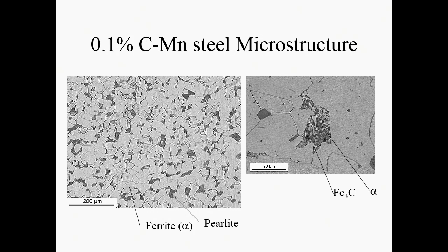With pearlite, the iron carbide is present in very thin layers and it's laminated structure, and this is a very tough structure, and this is very similar to the structures in seashells, what are called nacre, where you have a layer of ceramic and then a layer of a polymer and a layer of a ceramic. And the crack can go through the ceramic, but it stops when it gets to the polymer layer. And that gives very good toughness. And in this case here, the crack can go through the ceramic Fe3C layer, but it stops when it gets to the ferrite layer surrounding it. So it confers strength, but it doesn't reduce the toughness. In fact, it increases the toughness in some cases. So that's the microstructure of a typical structural steel, including a pipeline steel, before we start adding all the other alloying elements.